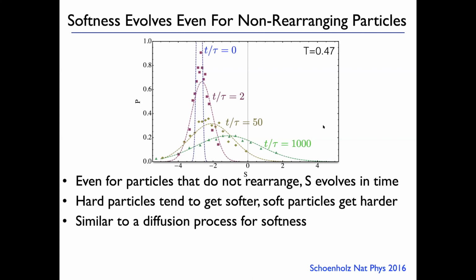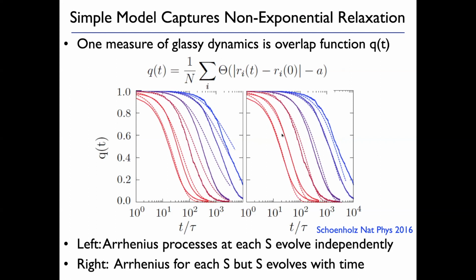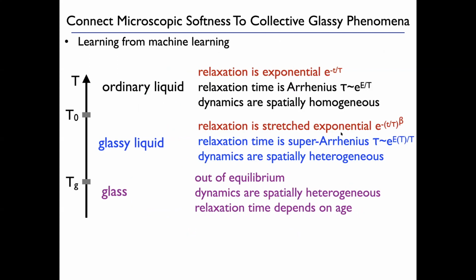And so we can just put in that physics. That's called facilitation, by the way. So a particle that wasn't soft can become soft because a particle nearby rearranges. We put that in, and put in that physics, and that does much better. So we not only see that the relaxation is non-exponential, but we have a decent theory for the shape of that non-exponential relaxation.